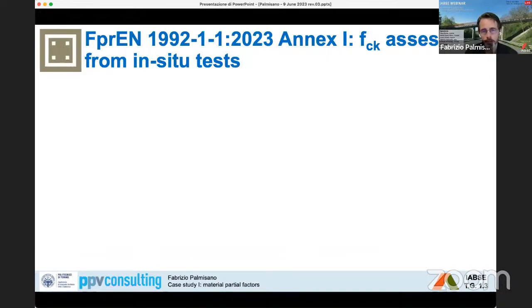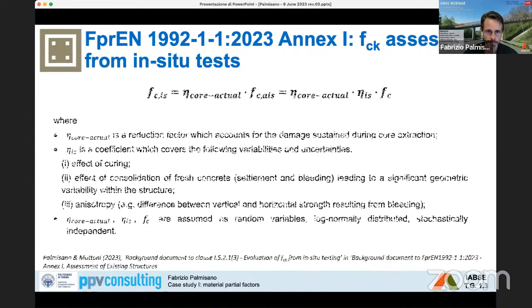Before starting to talk about the material partial factor, we have to determine the fck, the characteristic value of concrete strength, from in situ tests, because what we have obtained from EN 13791 is the value of fck in situ, obtained from tests on cores drilled from the concrete. However, all the formulations given in the code, for example in the Eurocode, make reference to fck. So it is necessary to pass from fck in situ to fck.